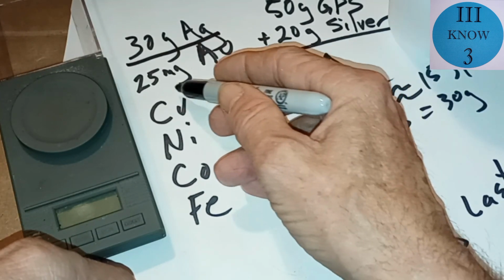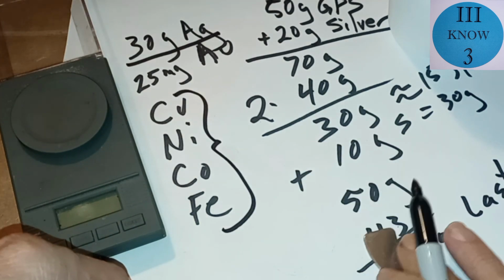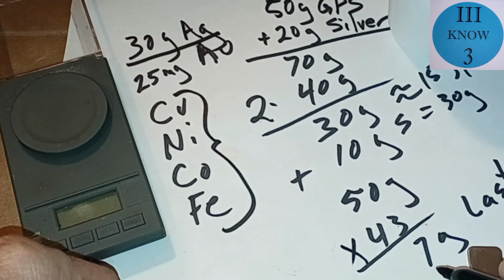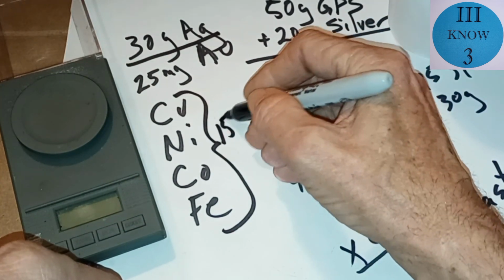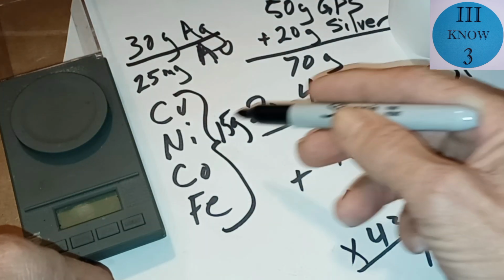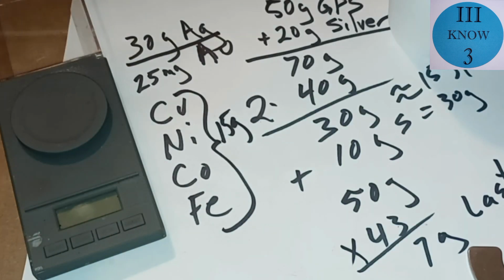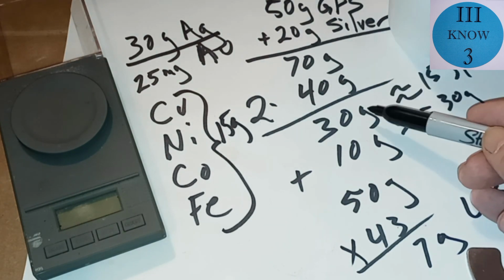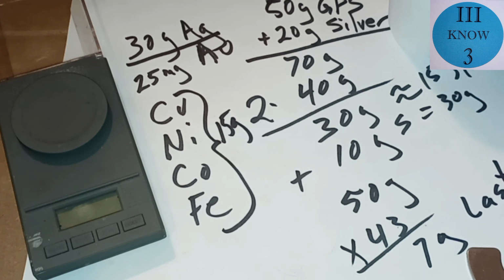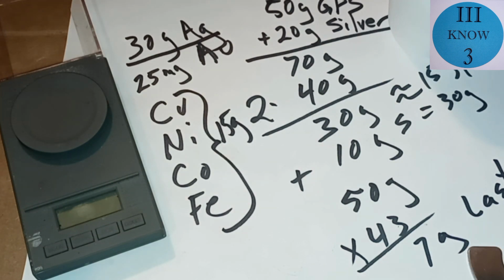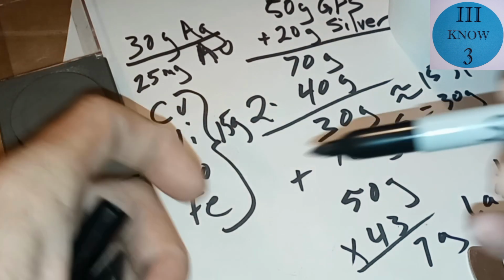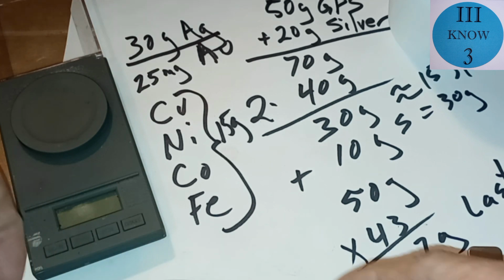That means that all of this, if we're down to say 43, we're looking at about 15 grams of all these metals combined left in this. And I would say our first 2 smelts were pretty successful because we were able to take out 15 grams per smelt into oxidized metals that we got into the slag. The last one was only moderately successful, but with the failure of the crucible and the reduced amount of time, I don't feel like we got a really good indication of what that would have been, since that one was without the sulfur and mainly just focusing on trying to oxidize the metal.